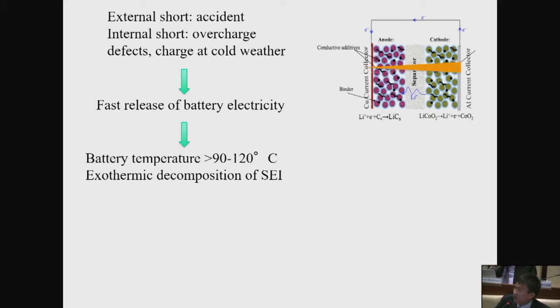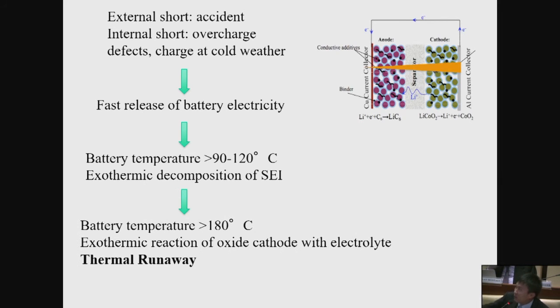At 100 degrees C, bad things start to kick in. You start to have exothermic decomposition of the solid electrolyte interface, the decomposition compound on each particle surface. At this moment, it's still not too bad. You can damage your battery, but it doesn't cause burning yet. But once the temperature inside the battery heats up to about 180 degrees C, you get an exothermic reaction between your cathode, a lithium metal oxide carrying a lot of oxygen, and the organic electrolyte. It goes through a thermal runaway. At this moment, you cannot stop the battery heating. It will automatically go on, catching fire and causing an explosion.